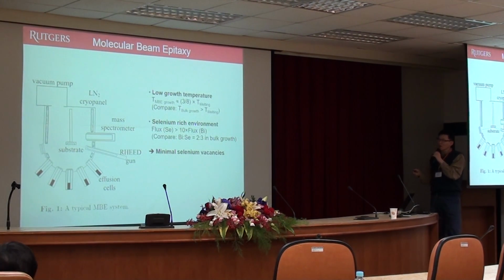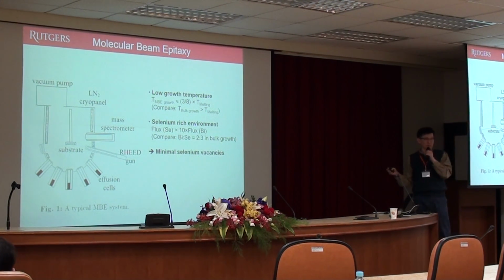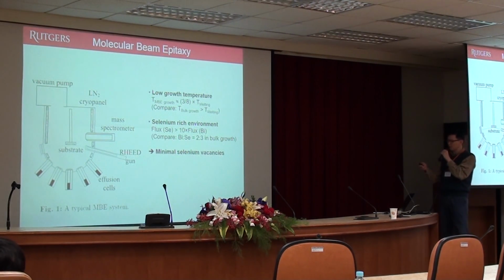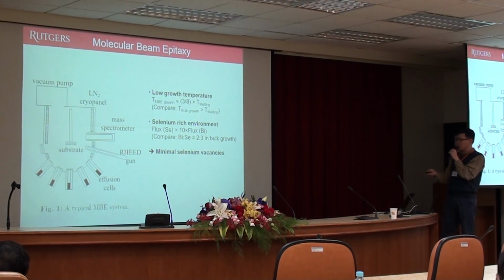And so especially for this kind of situation, MBE, there are other thin film growth schemes, but there is some advantage of using MBE because you can control a couple of things to your advantage. So the first thing is, compared to bulk growth, your growth temperature is much lower than the bulk growth temperature. Typically, the bulk growth should be done at the melting temperature, but because you are growing at a really slow rate in thin film form, your growth temperature can be much lower than the melting temperature.